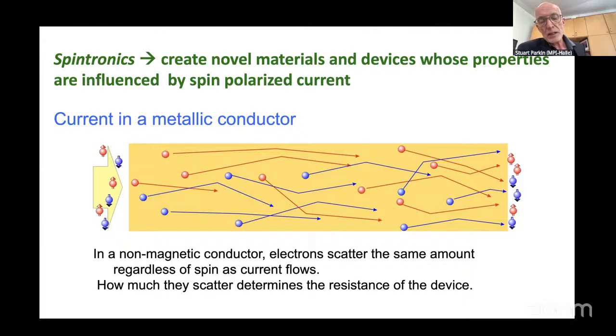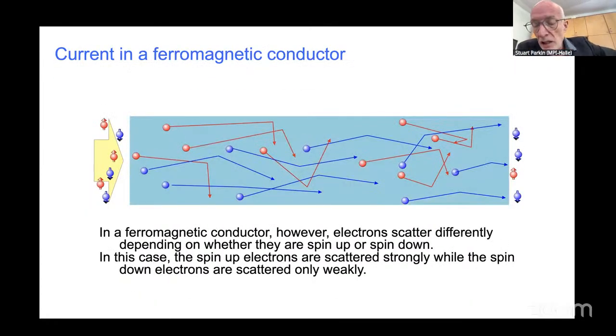So if you take a metallic conductor like copper, shown as yellow, and you introduce current from a battery on the left-hand side, then of course the current will be carried equally by spin up and spin down electrons, shown as these red and blue objects. And they will be scattered after some distance, which is the mean free path of the electrons. So now we take a material shown in blue, which is magnetic. And when you introduce current from a battery, initially the current will again consist of equal numbers of red and blue electrons. But because the scattering rates for the spin up and spin down electrons in a magnetic material are distinct, this means that after some short distance, the current will be carried by electrons of one spin type more than the other spin type.